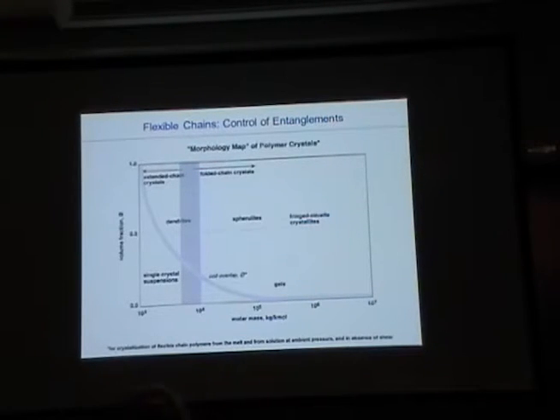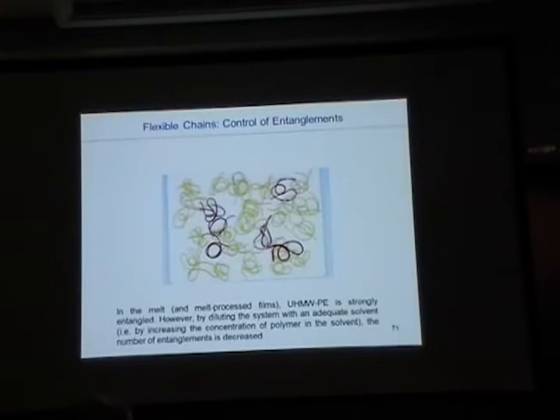What we often use in high-strength materials is gels. So these are materials which only have three entanglements per chain. Any guess why three? Why is three so important? Why not six or ten? Or two? One? You need three entanglements to get a network. If you have a stick, another stick, this would be an entanglement. Both molecules still can move. You need really three crossings. Why is that important? Once you have these gels, you can actually produce high-strength fibers.